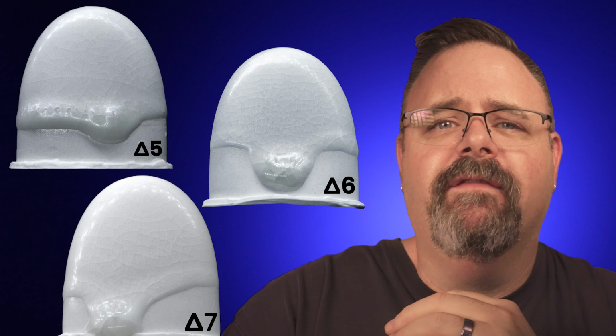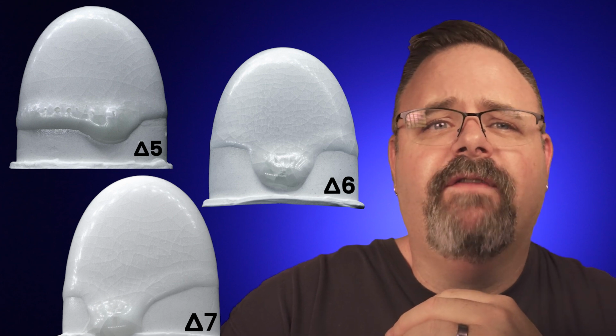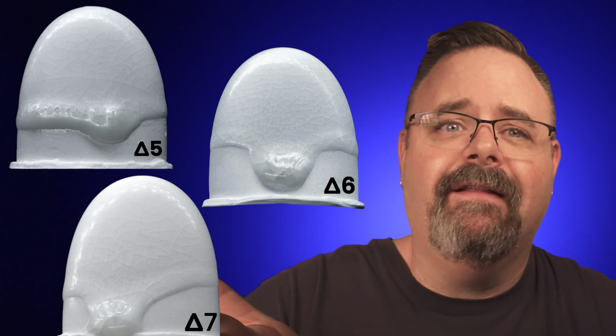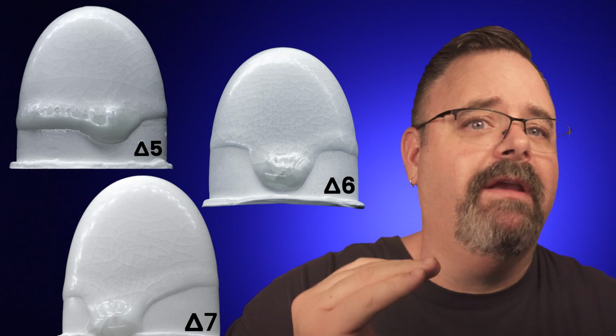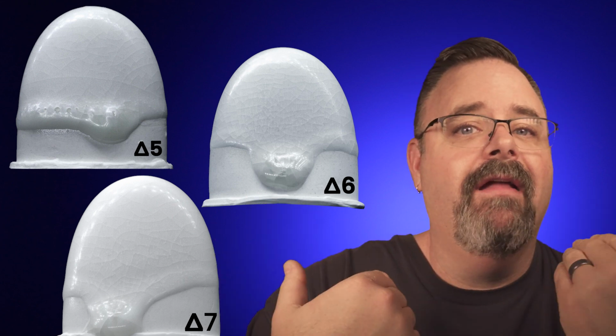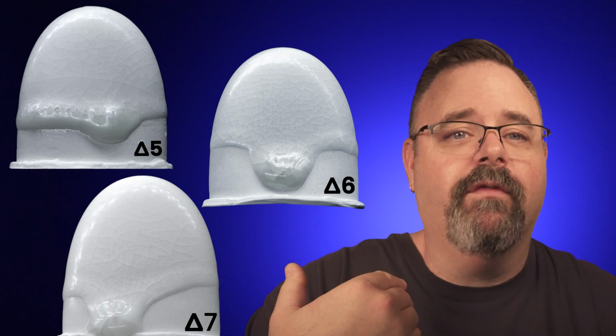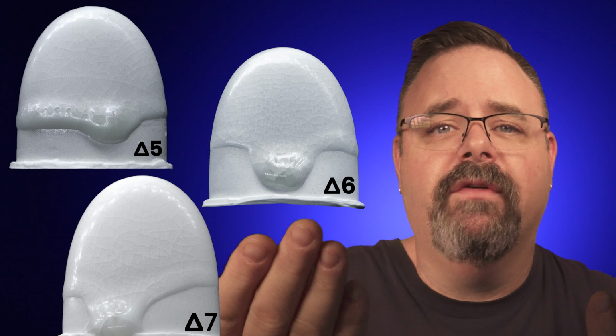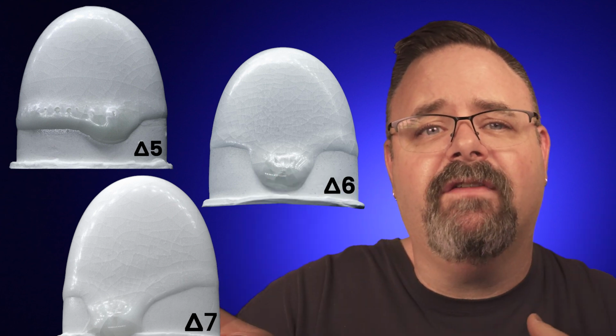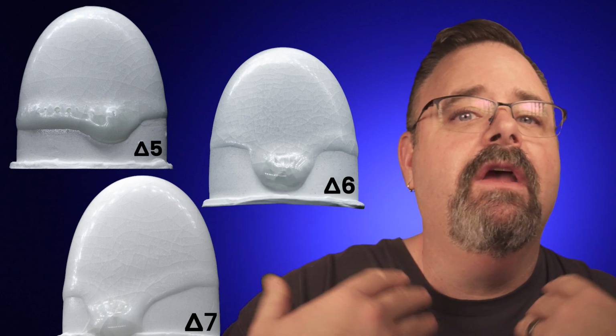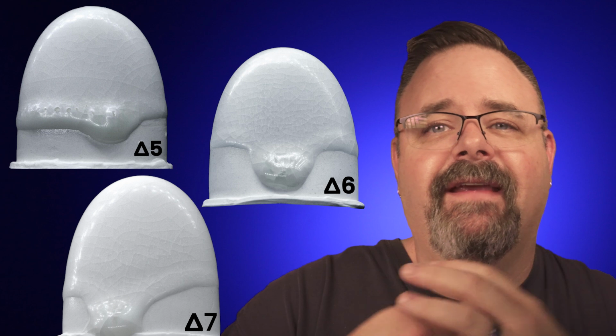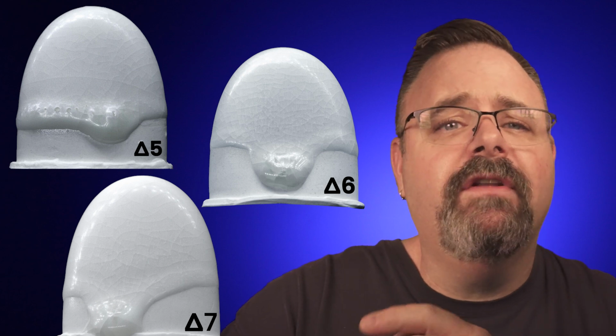Matte glazes don't care about how hot you fire them. These are all versions of the Katz-Burke matte, and they are just fired to different temperatures, and you see that the glaze is running. Well, glazes only run because they're too thick or overfired. This is an example of the glaze being overfired. This is a glaze that works best at cone 6, and when you fire it at cone 7, it starts to run really badly because you're dropping the viscosity of the glass and it starts to flow, and that's a bad sign. Matte glazes shouldn't be able to run because they're fully melted with crystals growing in them.